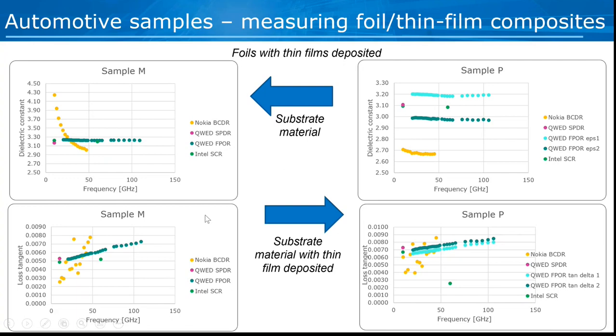The BCDR points zero down into a consistent value, and the loss tangent seems to more or less agree. On the right-hand side, we're showing that same substrate with a thin film coating on top, showing that different effective in-plane parameters are extracted from the SPDR and FPOR, and out-of-plane parameters are extracted from the BCDR.